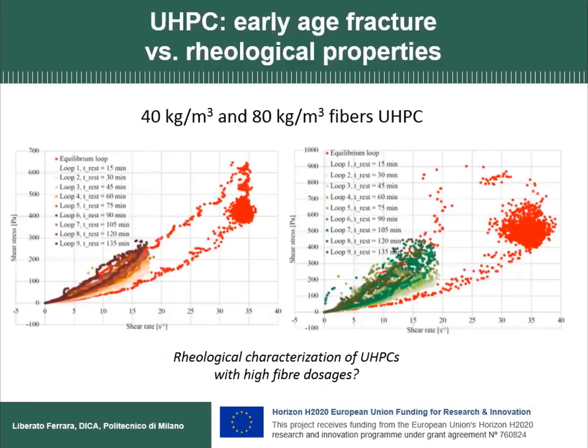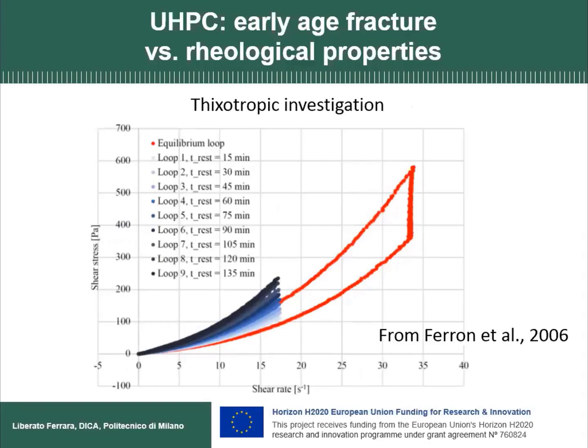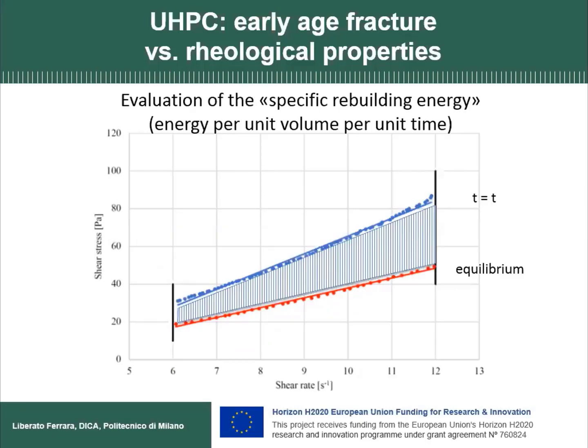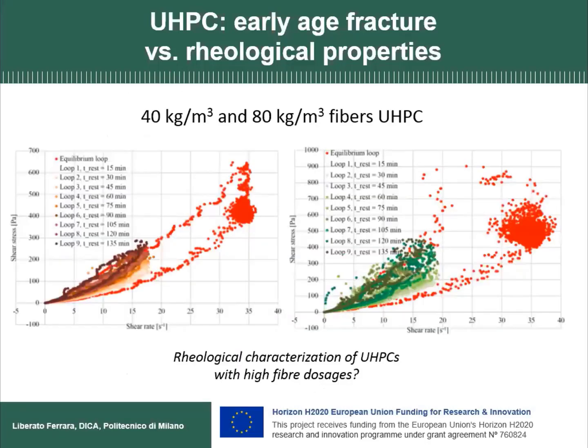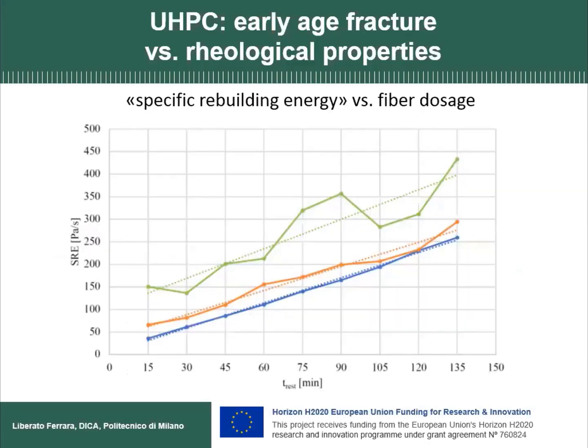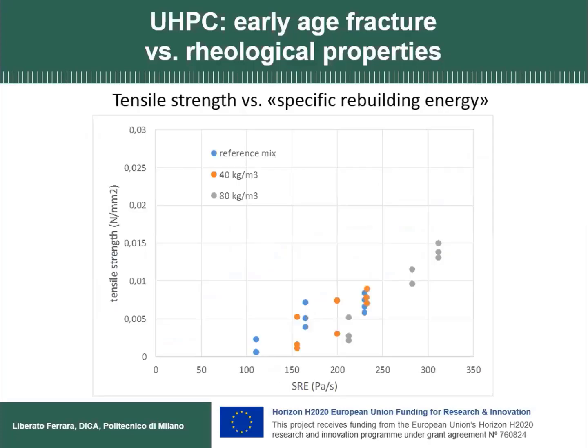You can see here the results that I showed previously. These are for the reference matrix, for the reference mortar, so they are quite regular and very good results, but they become a little bit more dispersed as the content of the fibers increases. So there is a matter of characterizing properly the rheology for increasing dosages of fibers. But as a matter of fact, there is a clear trend. The blue line is the reference mix, the orange is with 40 kilos per cubic meter, and the green, sorry, is a little bit more dispersed, but is the trend for 80 kilos per cubic meter. And you can see this energy increases with a regular trend with time.